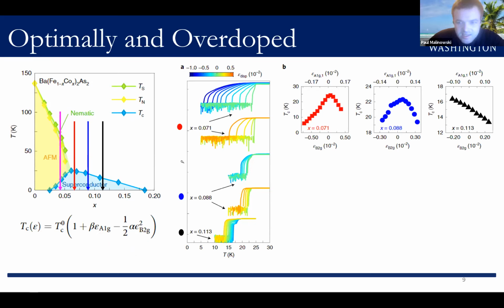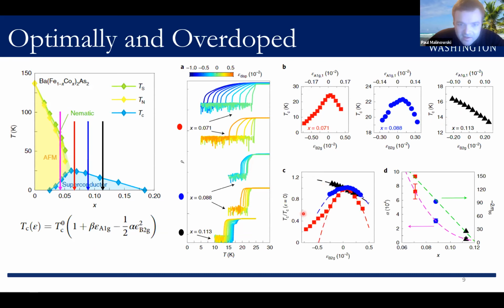And then symmetry dictates that TC can depend linearly on the A1g strains to lowest order, but only quadratically on B2g. So this evolution from quadratic to linear behavior is a signal of a loss of sensitivity of the superconductivity to the anisotropic strain as we move away from optimal doping. And we can quantify this by normalizing by the zero strain value, fitting a second order polynomial and extracting the coefficient alpha, parametrizing the sensitivity.